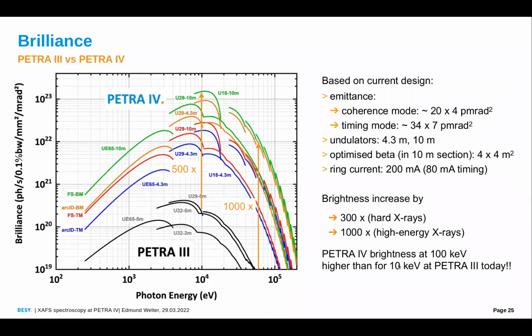The gain that PETRA IV promises is a huge gain in brilliance. We will gain about a factor of 500 at 10,000 electron volts, and about a factor of 1,000 for really hard X-rays, at about 80,000. Actually, the brilliance at 100 keV will be higher than the brilliance at 10 keV today. So that's a huge increase, especially at the higher energies.